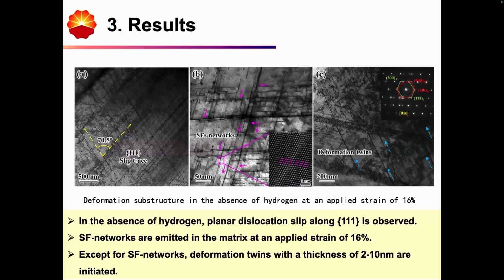Then we have some sub-microstructures. Since for the in situ charging, the specimen is fractured at a strain percentage of 16, here we first apply some deformation at an applied strain of 16 in the absence of hydrogen. So we can see some planar slip along 111 slip traces are observed.